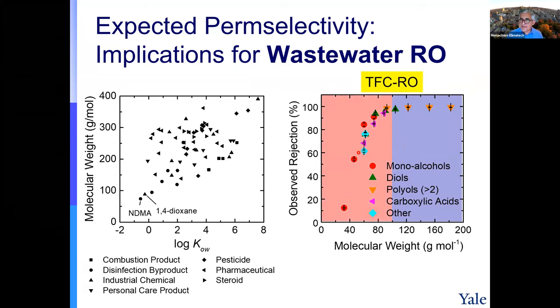So this is the area of low rejection, and let's project it here. The area of high rejection, high molecular weight, over 100, you see most of the organic contaminants, so not bad for them, except the NDMA and 1,4-dioxane that I mentioned that we have problem to remove. They're very, very small. So this is the current membranes. But again, we want really to focus on these small molecules, because we know pharmaceuticals and personal care products are quite large and they will not go through here.